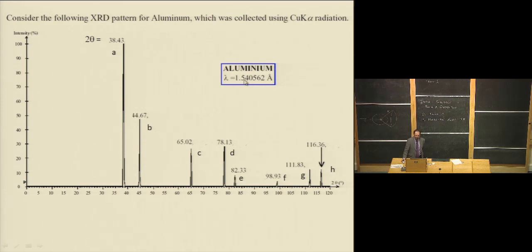And the wavelength is known extremely precisely in this setup. This is done with a typical X-ray tube. And they have 6 digits of precision as to how precisely they know the wavelength. Remember, the reason they know their wavelength so precisely is because this is an electronic transition between 2 eigenstates in an atom. It's an electron falling down from one eigenstate to another eigenstate, so the energies of those eigenstates are very, very precisely defined. So you know the wavelength with very high precision.